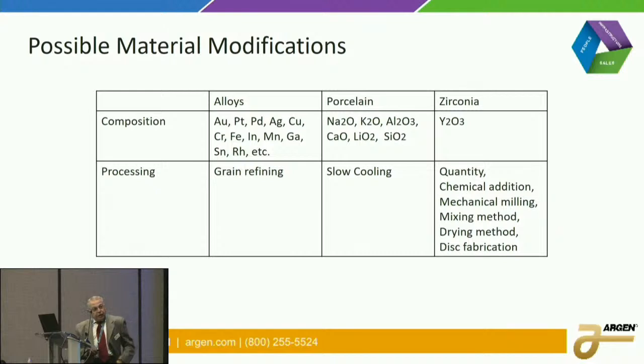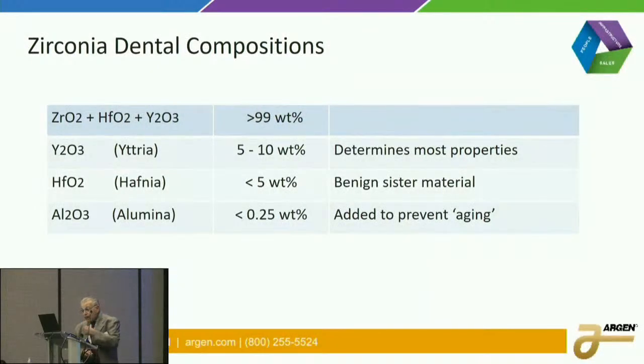However, with zirconia, the only thing we can work with here right now is the composition, adding the yttria, and we have different yttria amounts, which I'll show you in a few minutes. But the processing determines the majority of the properties. So this material is very different than what we're used to handling prosthetic devices. The actual compositions are very simple because of that.